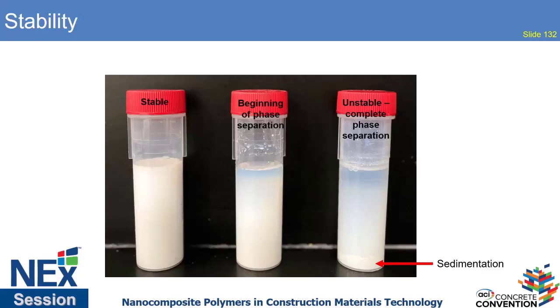At the beginning, when you have sedimentation, you can use mixing, sonication, or other methods to bring the material back. If you have agglomeration, you can bring it back so that you can stabilize the dispersion. However, as time progresses, you form more aggregates, and this becomes very difficult to disperse afterwards.